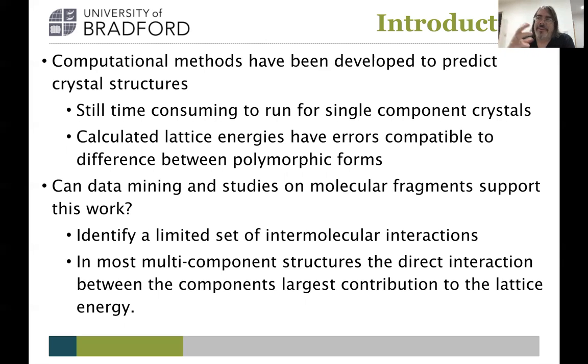And there's always the problem that at the moment, the lattice energies we calculate, even by DFT quantum methods, still have errors around 2 to 5 kilojoules per mole. So our errors in energies are still around the size of the differences in the rankings of the crystal structures for polymorphic forms, and we're adding that challenge to successfully rank and identify materials. So in terms of accelerating the process, are there ways of looking at components and fragments of the materials and predicting that rather than trying to do the whole crystal structure? Can we narrow it down to specific interactions?